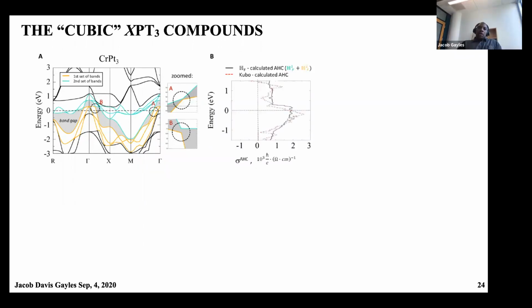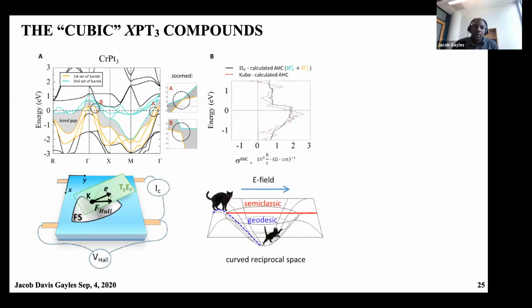What we can do is, for one, calculate the Kubo formula, which is shown here as a function of Fermi energy. And we also calculate what's called the hyperbolicity factor of this material. The hyperbolicity takes points on the Fermi surface and calculates the trajectory of these points. It's a new type of way that we were developing to calculate the anomalous Hall effect and transport properties. It's similar to how a cat moving on a geodesic surface will follow the path of the surface as described here.